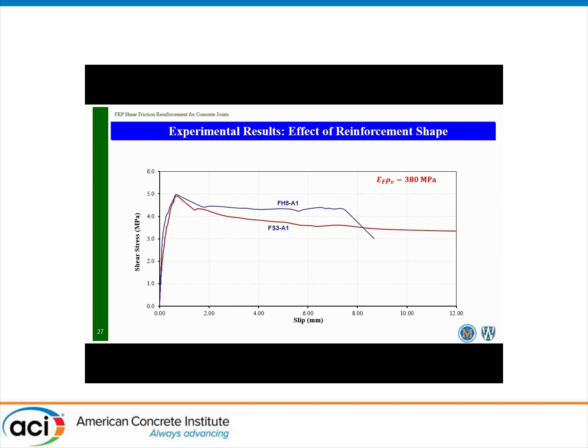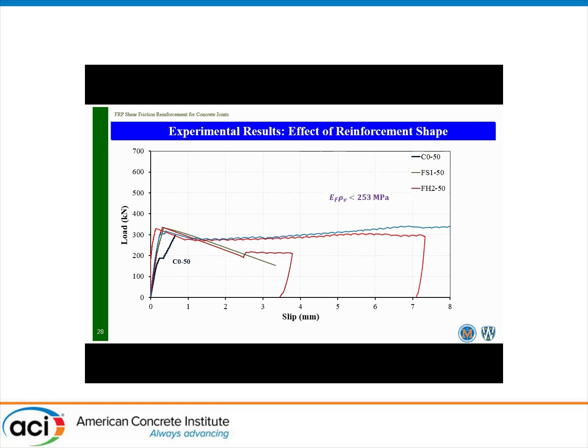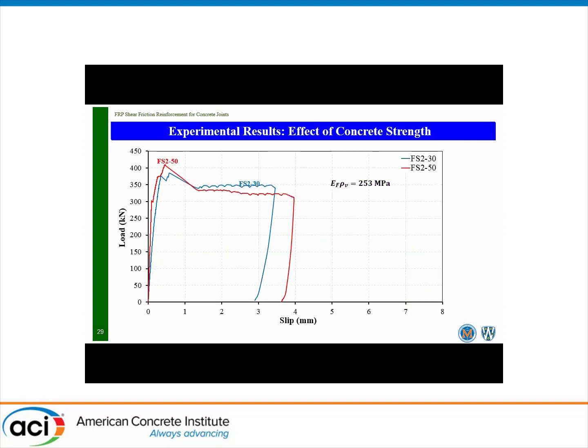In terms of difference between shape and effective shape, these two specimens with the stirrup and with the headed bar both have the same stiffness parameter, and they show almost the typical indication. So it's not the shape, it's the reinforcement content or the stiffness of the provided reinforcement. All these specimens with stiffness-inadequate reinforcement failed suddenly later on after cracking.